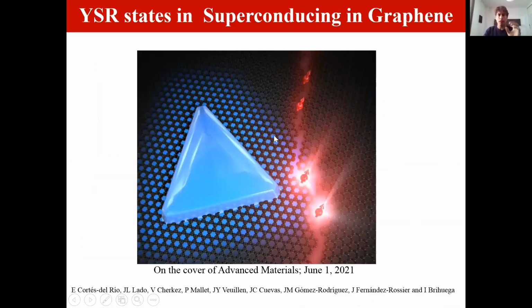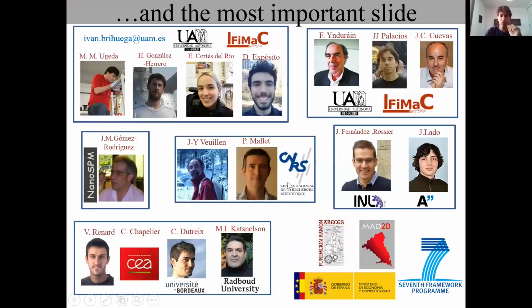That's theory. So just to summarize this part of the talk, we had a lead island that induced superconductivity on some graphene regions, and at the same time we had a grain boundary. In the grain boundary, which naturally exists on graphene, we have local magnetic moments, and when we have the coexistence of those local magnetic moments and superconductivity, we have the emergence of Yu-Shiba-Rusinov states. So we really have the ingredients to make graphene a very good platform for making, for example, topological qubits or similar things. So I just finished. Jose, don't worry.